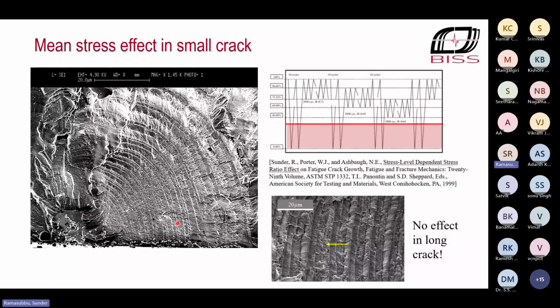Many years ago, about 25 years ago, we were doing an experiment on natural crack formation at the notch root. And we used a load sequence that is shown over here. We wanted to see whether there is a mean stress effect when there is no crack closure. And we were surprised that in a naturally forming crack, now that is a notch root, that is a particulate near the notch root from where the crack took off.